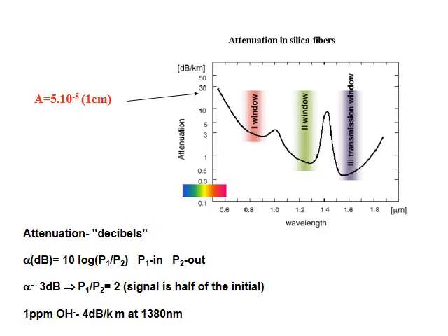A normal spectrophotometer that we use in our lab is not able to measure such a low absorbance. Our spectrophotometer here in Araraquara is able to read values of absorbance of 10 to the minus 4. And in addition, as we already said, the visible is not the region of minimum absorbance. In the infrared, considering 1 centimeter optical path, the absorbance of a silica glass will be 10 to the minus 7. For 1 centimeter optical path, this is really nothing.